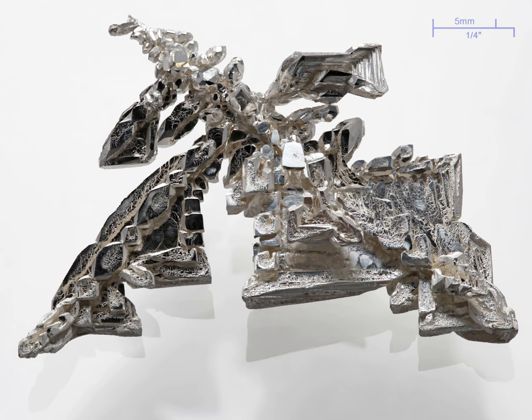The fluoride, chloride, and bromide have the sodium chloride structure, but the iodide has three known stable forms at different temperatures, that at room temperature being the cubic zinc blende structure. They can all be obtained by the direct reaction of their respective elements. As the halogen group is descended, the silver halide gains more and more covalent character, solubility decreases, and the color changes from the white chloride to the yellow iodide as the energy required for ligand-metal charge transfer (X-Ag+ to XAg) decreases.